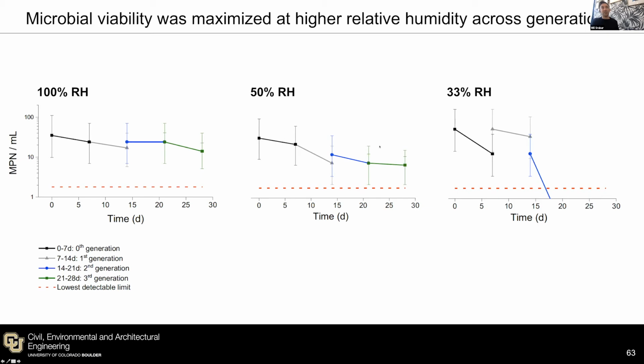The same was true for 50% relative humidity, which is even lower than what the humidity is in most buildings. We keep the humidity at about 55% and up to 65, maybe even 70%, kind of narrow window where humans like to be comfortable. And obviously, if we dried it completely out after the second generation, the bacteria ultimately died because they were super stressed from a lack of access to moisture.